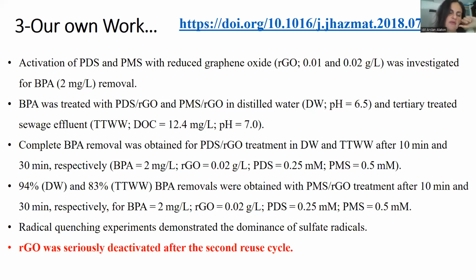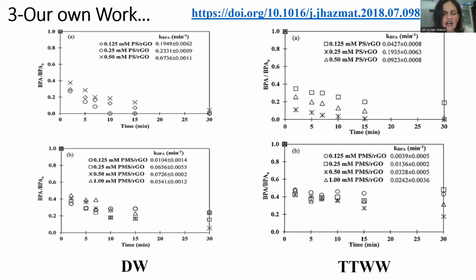But the problem was the catalyst was seriously deactivated even after the second reuse cycle. I'm not going to show that. Here I show you the comparative results in distilled and in tertiary treated wastewater. You can see that reaction rate coefficients are indicated for bisphenol A removal. The results are slightly better, the oxidation rates for persulfate this time. And of course, in tertiary treatment, we have some inhibition, but it is not so dramatic. The problem was that we could not reuse the catalyst. So with reuse and recovery, I mean here, filtration, centrifugation, and rinsing with distilled water and just drying. That's the recovery procedure, and using again.